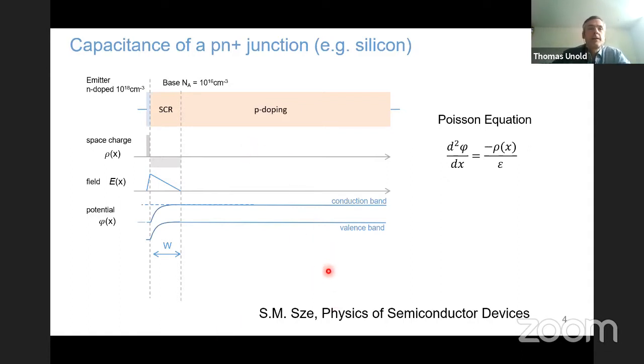So I show here basically a silicon PN junction based on a silicon wafer. This is where this technique was actually developed. And where you have there usually a very highly doped emitter and then a lower doped base. And then you form a PN junction, which means you have a space charge region here. So this is the space charge of one type and space charge from the other type. And this must balance. So that's a condition.